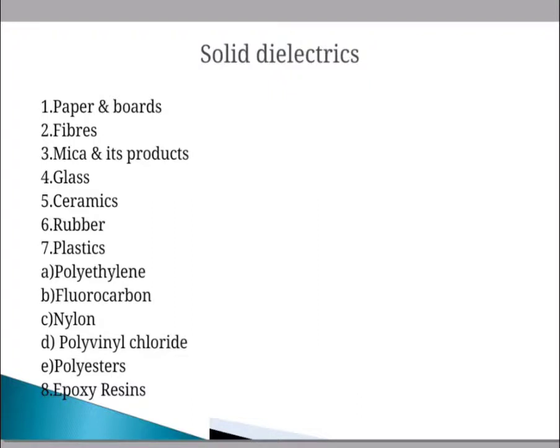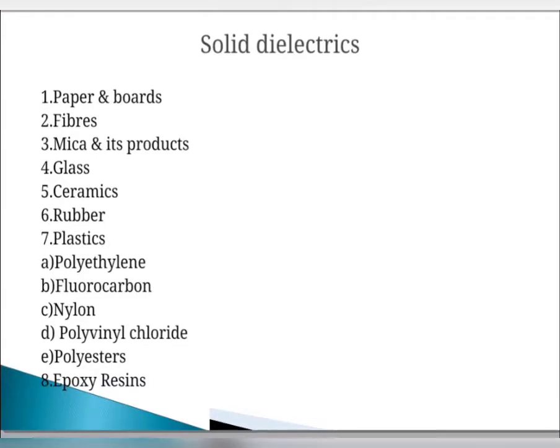Polyvinyl chloride (PVC) is used commercially in various forms — as unplasticized, rigid sheet material — and can be easily shaped to any required form. It is chemically resistant to strong acids and alkalis, and insoluble in water, alcohol, and organic solvents like benzene. The upper temperature limit of operation is about 60°C. The dielectric constant and loss tangent are 3.0–3.3 and 0.015–0.02 respectively at all frequencies up to 1 MHz.